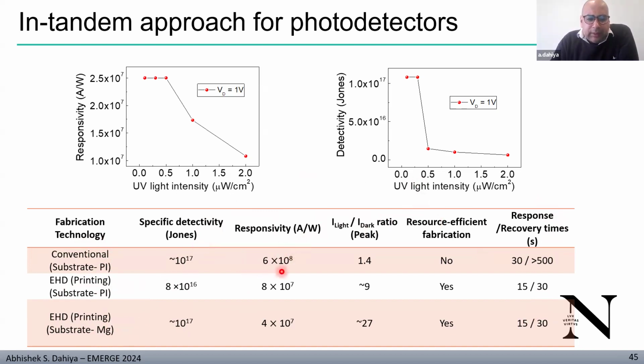In terms of responsivity, of course, conventional was better because of the more efficient current transport at the metal semiconductor interface. But because the dark current was higher as well, the on-off ratio was poor. And it also takes a long time to respond and to recover compared to the printing. In printing, responsivity is okay, a bit lower than the conventionally made, but the on-off ratio was better than the conventionally made because of the rectifying contacts you get at the metal semiconductor interface for the nanowire and the printed gold.